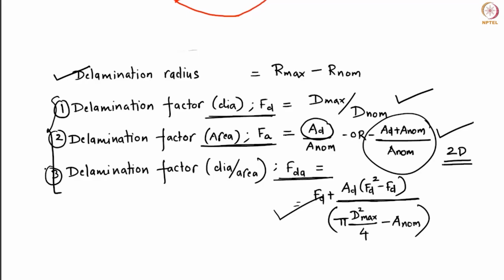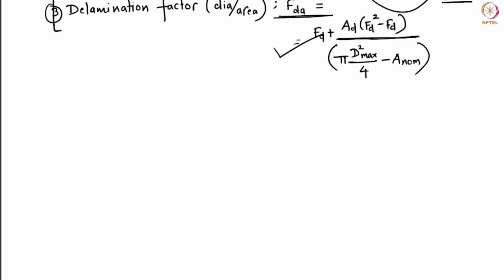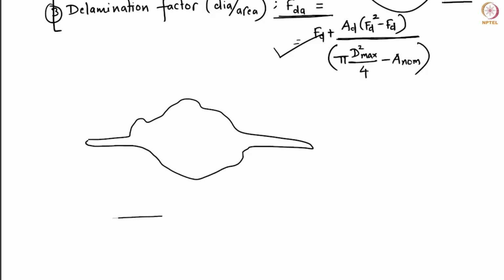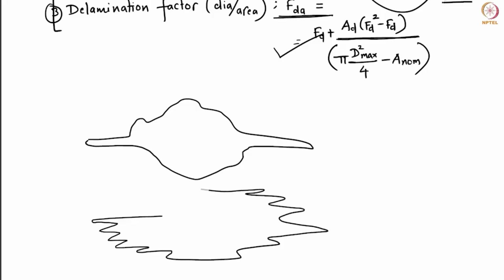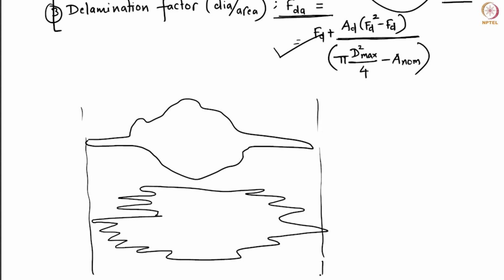However, you can already see that if somebody gives you the value of the delamination factor, from that you may not be able to actually calculate the actual damage. Sometimes completely different looking areas may have the same delamination factor. If you have one long strand that is delaminated, then the diameter based delamination factor can give you different values for different kinds of delamination. For example, in some structures the maximum value remains the same, but the delamination can actually be of a very severe nature. If I calculate the diameter based delamination factor, because I'm just calculating the area of the bigger circle, it will still give me the same value.